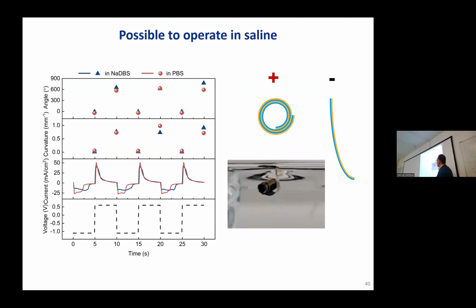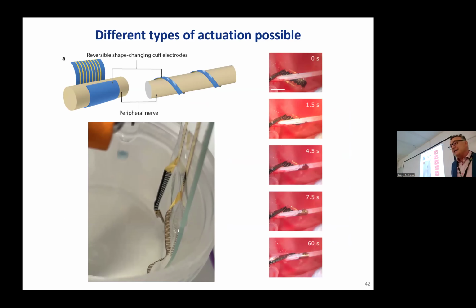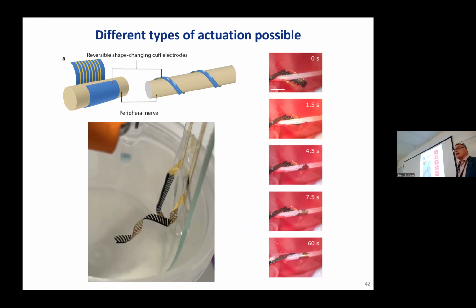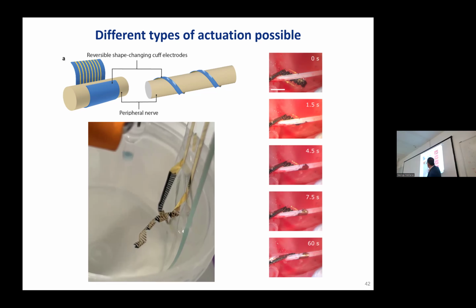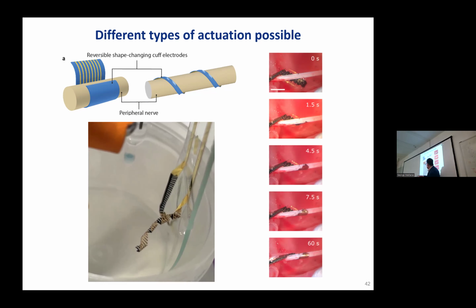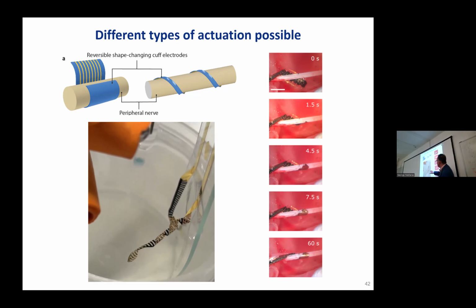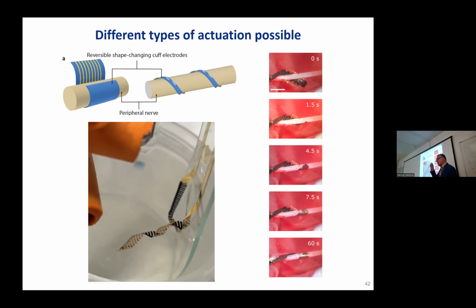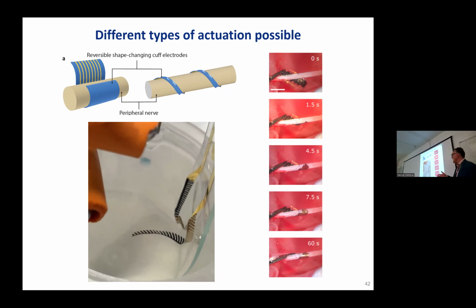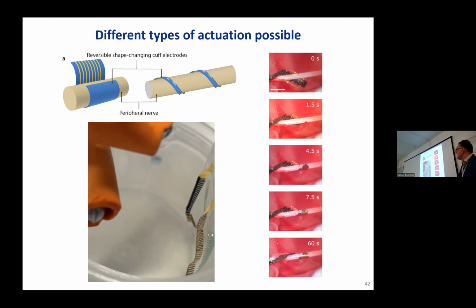So what happens here is you apply a voltage, ions would come into the film, you see a current that flows, and then you would change the angle at which the film is curved. By engineering the shape of that conducting polymer, you can get the implant to do different motions. For example, here is a helicoidal type of rolling motion that was engineered by having fingers of conducting polymer at a slight angle with the axis of the implant. And by controlling the angle, you can control the pitch and all that. So this is a device that you can present to a nerve, as shown here, and then get it to wrap around the nerve very gently.